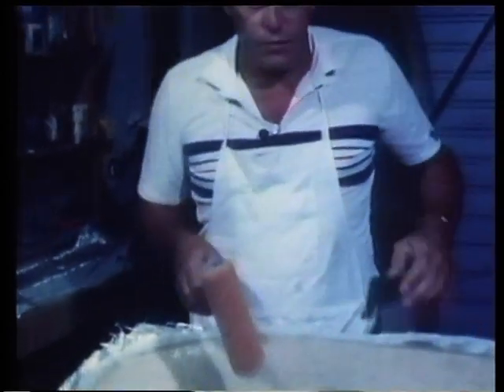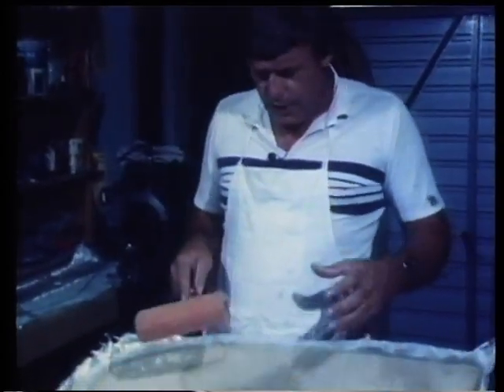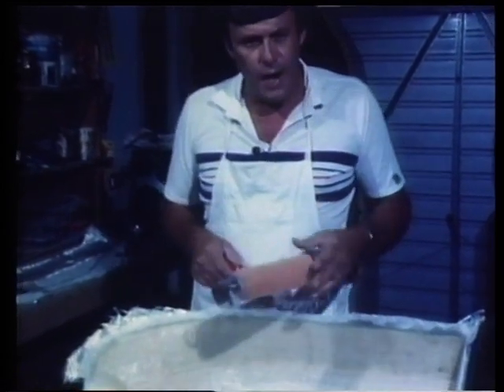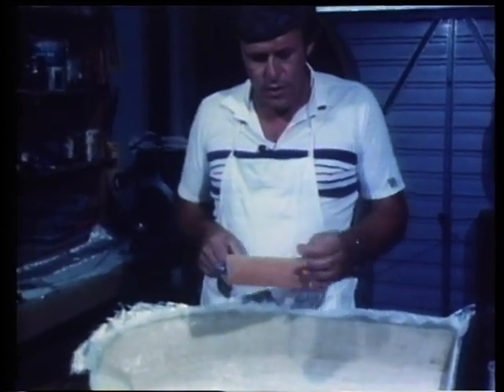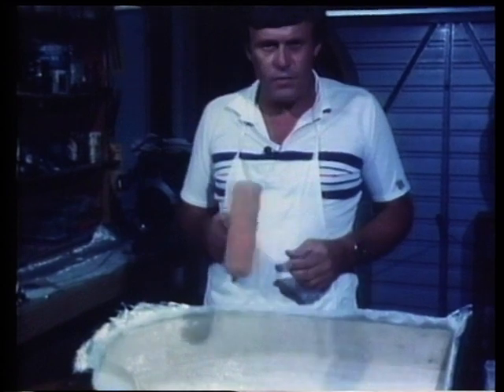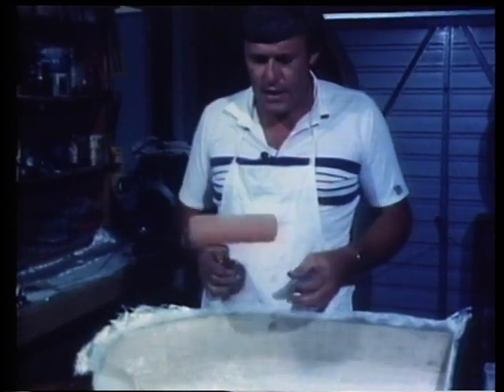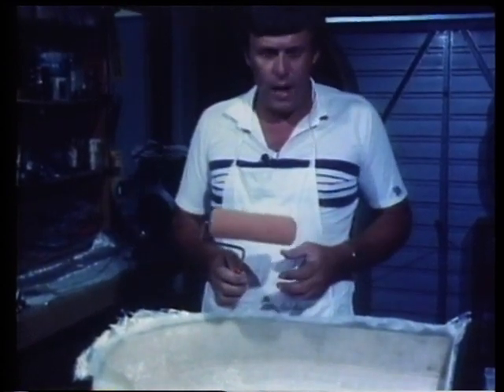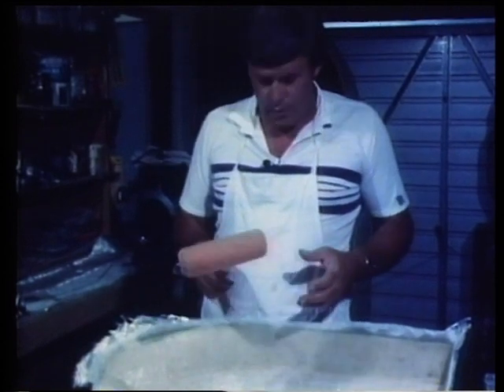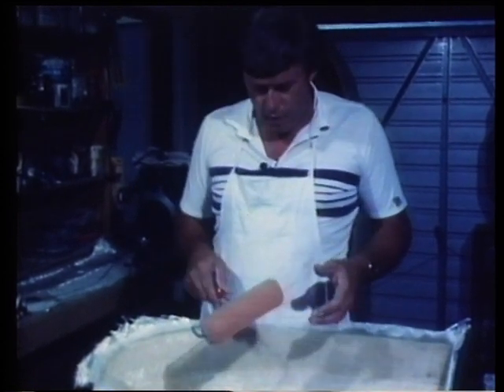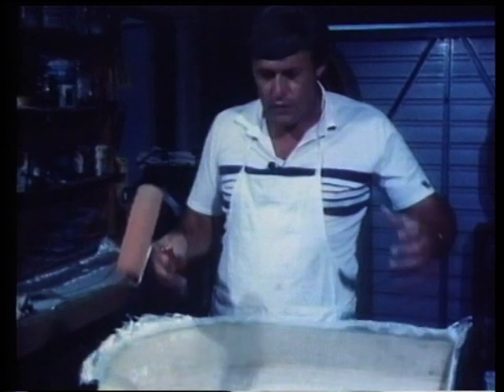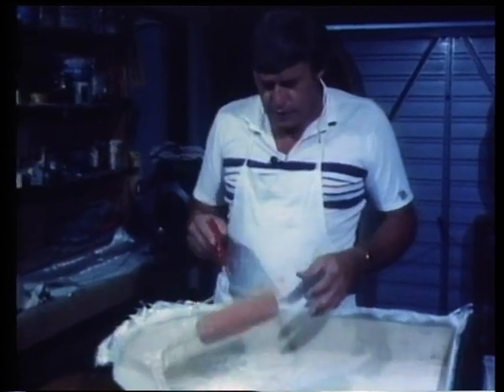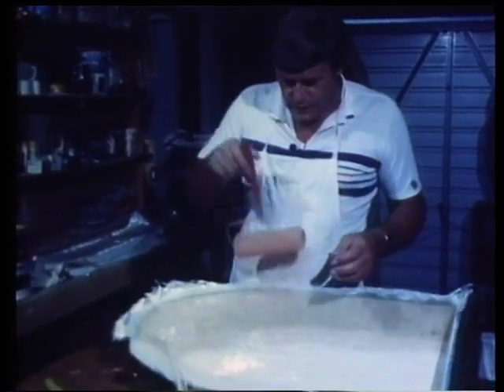But before I go, one of the confining factors with using a mould like this is the fact that because of its small size, we can't use some of the equipment that's used on the bigger boats. Now, the application of the resin on larger laminates is taken over by that specially made fiberglass paint roller, and it is exactly a paint rolling technique. You have your normal roller tray with your catalysed resin in it, you dip your roller in it and you roll it down into the mould.